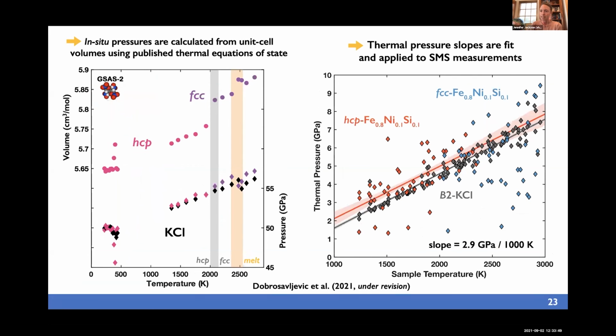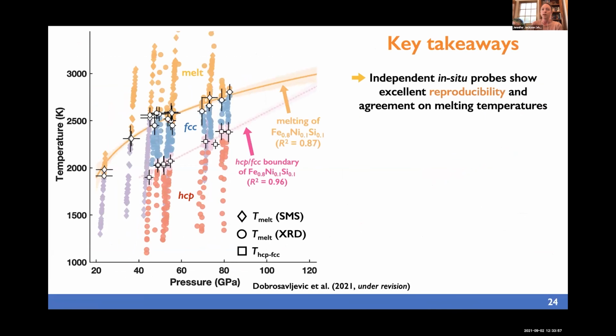We also use in situ pressure measurements of the sample and KCl. And this leads to very good agreement and reproducibility of the melting. So here we show all the melting runs and the FCC to HCP boundary.